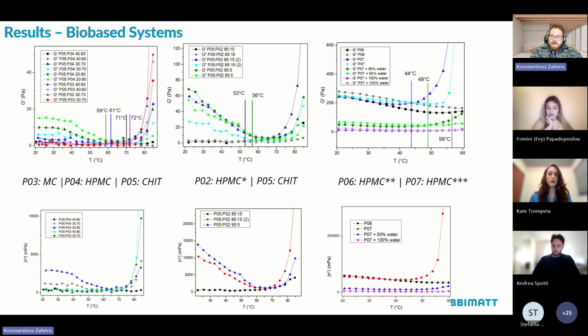As you can see in this slide, at low temperatures, all systems comprising either methylcellulose, hydroxypropyl methylcellulose, or chitosan exhibit low storage modulus values, which indicates weakly structured networks. As temperature increases, a sharp rise in G prime can be observed in some cases, which corresponds to the thermally induced gel formation. However, the key observation here is that this transition occurs at relatively high temperature, typically between 50 to 70 degrees Celsius, depending on the composition of the hydrogel.